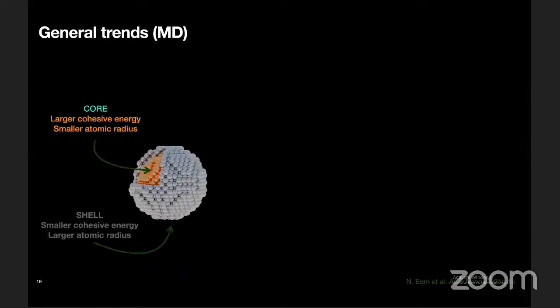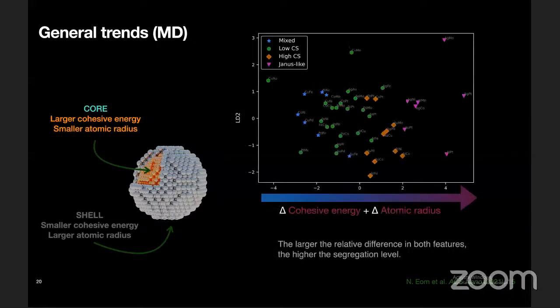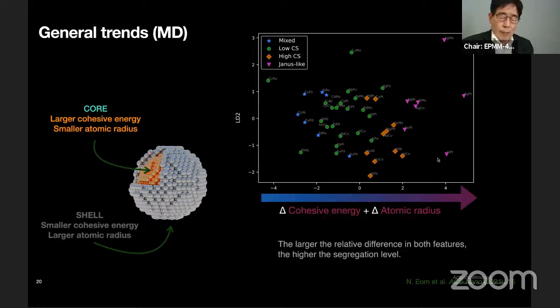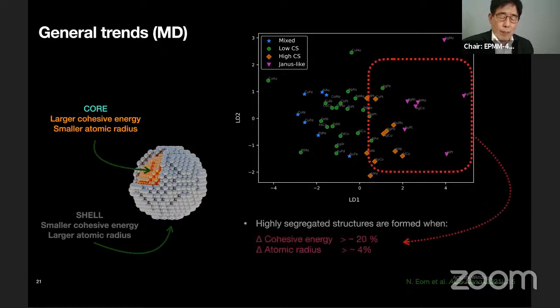The first general trend we see from the analysis agrees well with the previous studies: for a given combination, the material with larger cohesive energy and smaller atomic radius tends to occupy the core, and the other occupies the surface. And it was true for the majority of the combinations that we studied that the element with larger cohesive energy usually has the smaller atomic radius. And the larger the relative difference in both features, the higher the segregation level. And we could also see roughly how large the relative differences should be for a combination to form highly segregated structures.